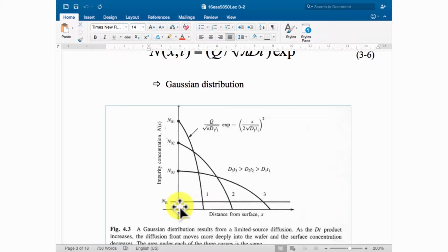They don't add more. So you can see the concentration on the surface will keep reducing, right? Because as time approaches, the impurity will go deeper into the substrate. It penetrates into the deeper area. However, the surface concentration will be reduced because you have a limited source of diffusion. So the area under the curve will be the same.